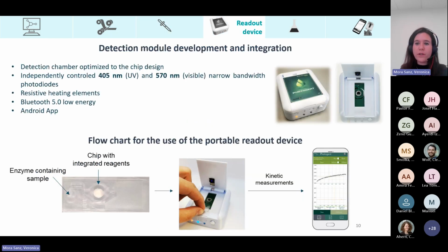So, as I said before, during the project, we developed a customized colorimetric reader with the detection chamber adapted to the chip design. This reader is able to measure absorbance at 2 wavelengths, at 405 nanometers for amylase and at 570 nanometers for cellulase. It also incorporates heating elements and Bluetooth connection, allowing it to be controlled by a smartphone employing an Android application. Here we can see the flowchart of how we use the portable reader with the chip.